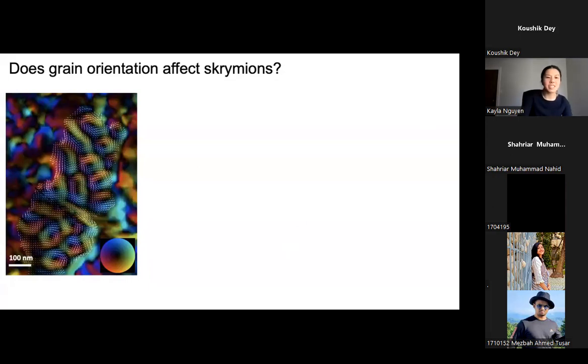Yeah, that's a great question. Thank you for asking. I think the answer is yes, there is a technique out there. There was a recent paper in Science that came out in 2021. It's called multi-slice ptychography. What they're doing is taking the electron beam and diffraction pattern projection, and modeling the probe as it changes through a three-dimensional structure. So they can get back the atomic slices at each thickness of your sample. And you can see that the atoms in your sample are actually vibrating depending on what thickness within the crystal you're looking at. So that's one way. It's a really groundbreaking technique, because now we can solve so many problems in 3 dimensions just by looking at our projection of our diffraction pattern.